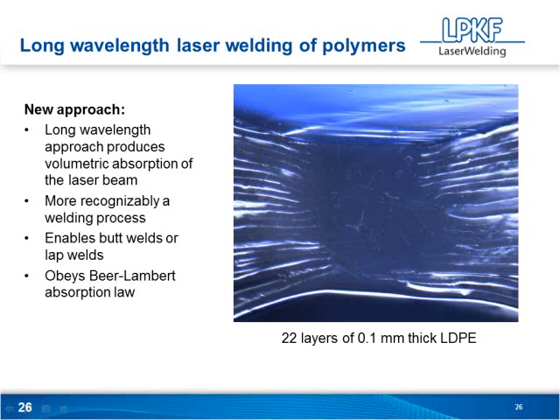And to go back to Josh's discussion on this particular slide, we've shown welding up to 22 different layers of 0.1 millimeter thick LDPE. One of the reasons I did this was because it actually shows the outline of the weld volume very nicely, and it shows that it obeys the classical Beer-Lambert absorption law as expected from first principles. And it is actually more recognizably a welding process to those of you that are familiar with metal welding. It's a similar mechanism in that you're melting a complete pool of material and moving that through the material.